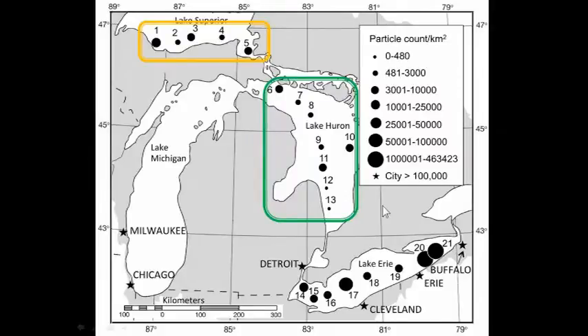Regardless of these numbers, though, the vast majority of what we collected was found in Lake Erie. So 90% of the plastic that we collected in total from the 2012 study was all collected in Lake Erie. You'll see samples 20 and 21 had our highest counts, on the order of 2 times higher than most oceanic samples. There's actually only one number reported in literature from oceanic studies that's higher than these counts that we found in the Great Lakes. So, much higher counts than you see in most oceanic studies. And granted, it's only 2 of our samples, but it's very interesting to find such high counts coming from the Great Lakes.